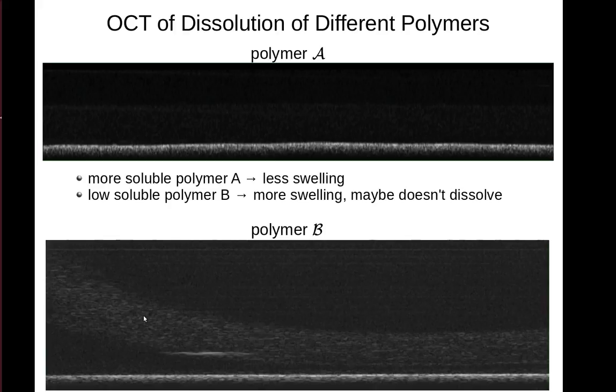It turns out that Polymer B is relatively insoluble in the buffer solution, whereas Polymer A is soluble. So therefore Polymer A swells and then finally dissolves, whereas Polymer B swells but doesn't dissolve. The OCT measurements are not done under flow due to some of the problems with reflection of the surface with ripples. Therefore the QCM does show slightly different results, where the flow probably causes the undissolved polymer to eventually just rip from the crystal surface and float away.